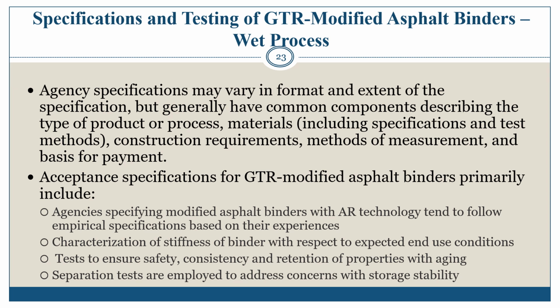Acceptance specifications for GTR modified asphalt binders primarily include test results to characterize stiffness of the asphalt binder with respect to expected in-use conditions, complemented by tests to ensure safety, consistency, and retention of properties with aging. Separation or settlement of GTR from asphalt during storage is a common concern. This is primarily due to issues with buildup of GTR in storage tanks with intermittent or sporadic use of GTR modified binders. Precautions and measures can be used to reduce or eliminate settlement issues.